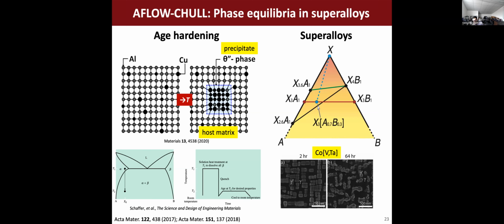There are some synthesis pathways where if we quench, for instance, we can actually achieve non-equilibrium states. And how long this non-equilibrium state lasts depends on the material, on the kinetics of the material. So this analysis is in a sense a bit independent of our synthesis pathway, but it's important to realize that the kinetics of the system is an important component. This is a bit outside of the thermodynamics. However, if we allow the system to realize its ultimate thermodynamic state, the minimum energy state, these results would be the ones we would expect. So your question is more involved with the kinetics of the system. I hope that helps, as a former experimentalist.